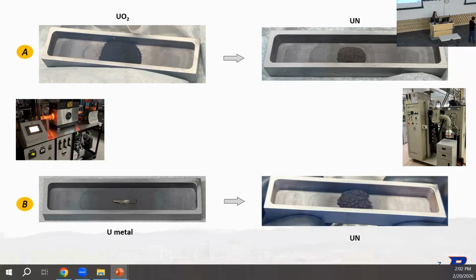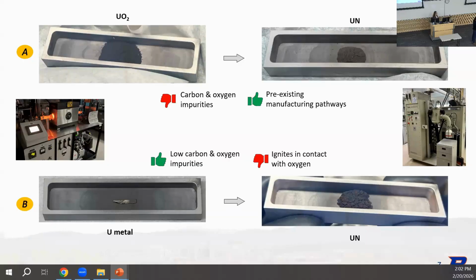And these are the actual furnaces in my lab. The other technique uses uranium metal, still in the same tube furnace, which then gives us UN, and then we can use that again to sinter. So our goal is to look at the characteristics of these. At a broad overview, synthesis route A gives us carbon and oxygen impurities because we are mixing carbon in deliberately. We also get to utilize pre-existing manufacturing pathways, which is a big bonus.